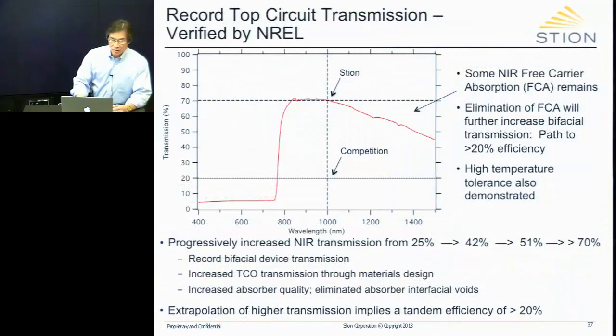So this is the transmission of the entire top device. And this is a spectrum taken by NREL. You can see that the band gap is near 1.6-something eV, and near 1,000 nanometers it is about 70% transmissive, and near 1200 it's about 60 or so percent transmission. That may not sound like a lot to you, but typical tandems that you see out there are on the order of about 20% transmissive in that region. So we are over 3 times more transmissive than the others.